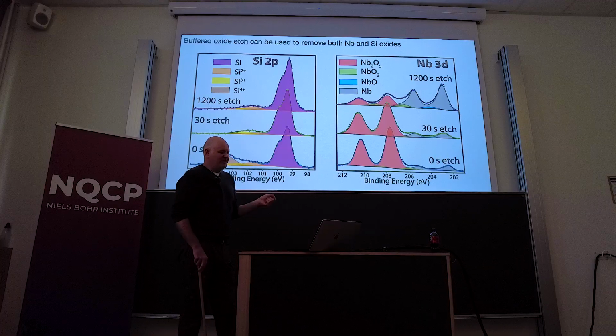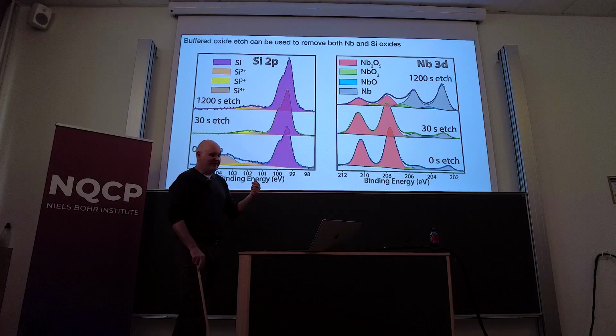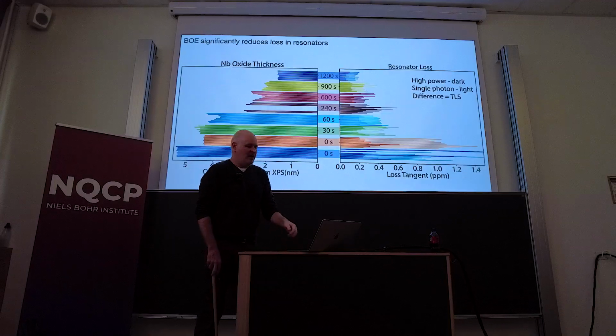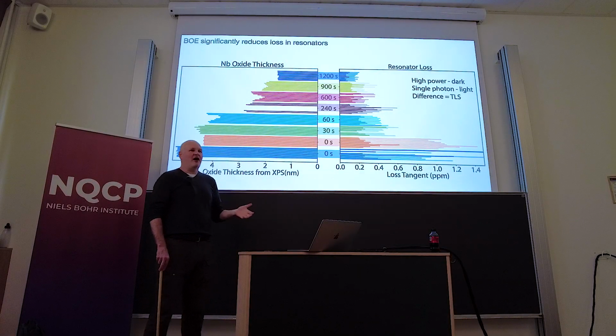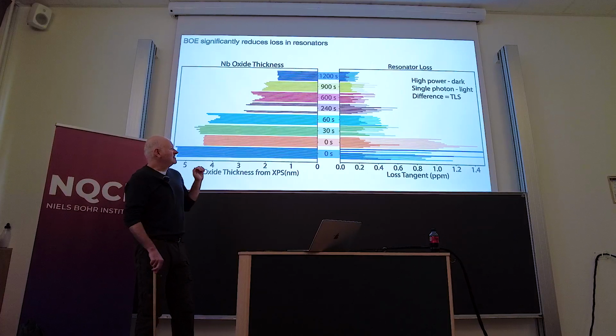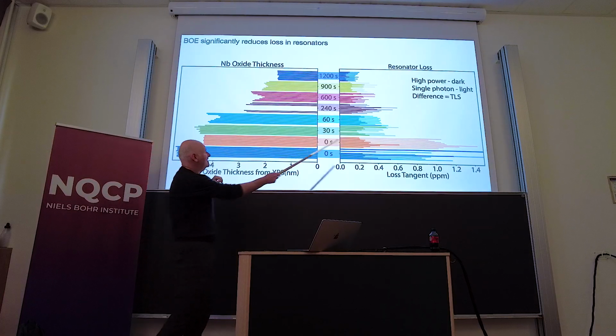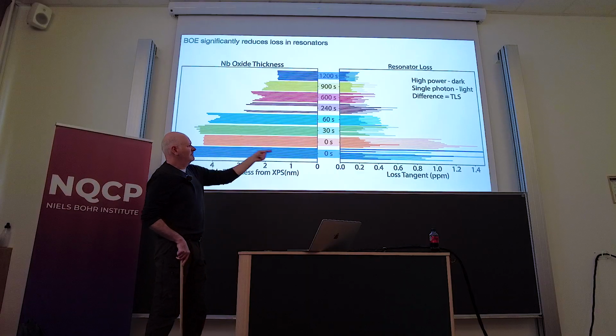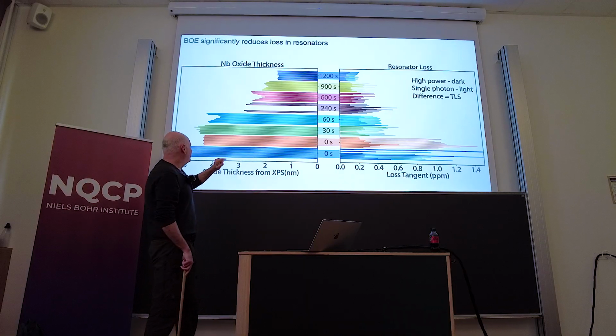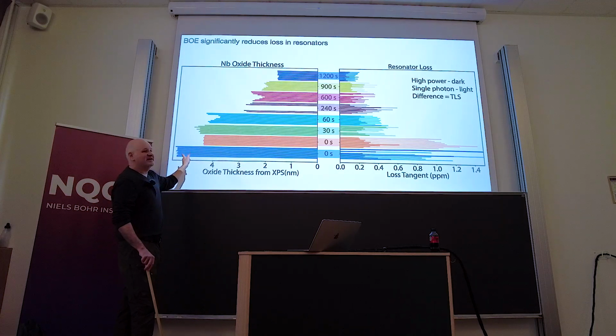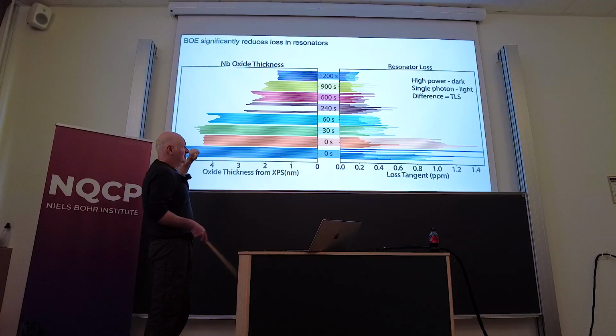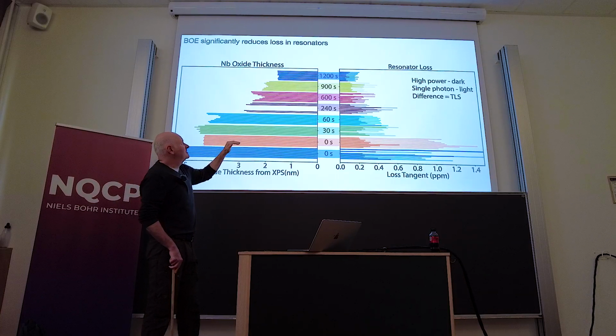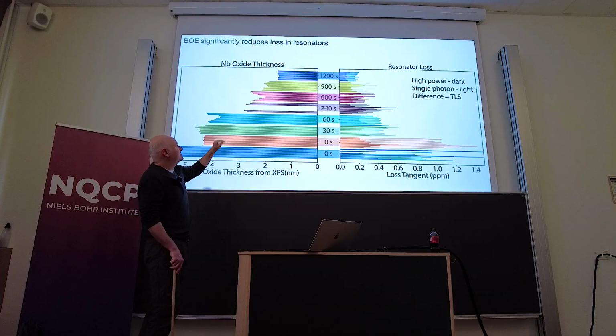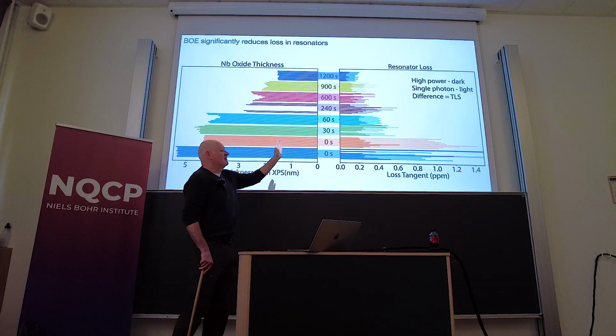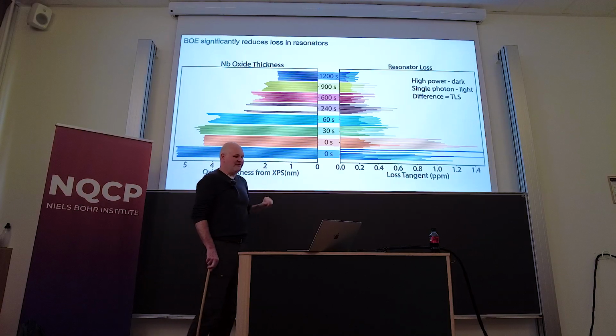So what we did is we took these samples, ran different dip times on resonators that had been fabricated. So these are all RF resonators, and we're looking at the resonator loss on this side. So longer bar means more loss, and this side, the thickness of the oxide. So longer bar means more oxide. And there's a correlation. So as you go to longer and longer etch times, you get less and less niobium oxide and better and better resonator loss, less resonator loss essentially over time.